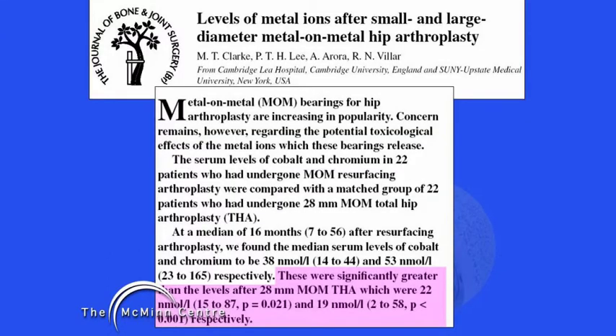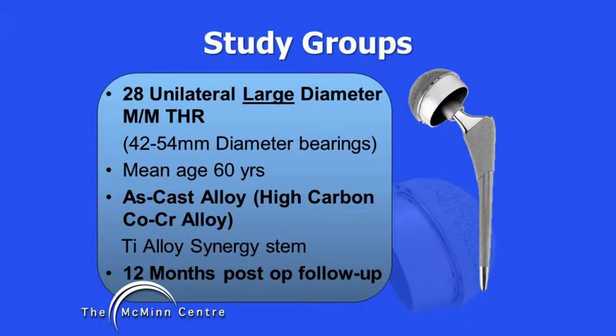However, this study suggests that small diameter metal-metal total hips produce lower metal ion levels when compared to large diameter metal-metal bearings. We had great doubts about the methodology used in this experiment and decided to initiate our own study. The first group are 28 unilateral large diameter metal-metal total hip replacements. These have an as-cast alloy bearing with a titanium alloy stem and were followed up at 12 months post-op.